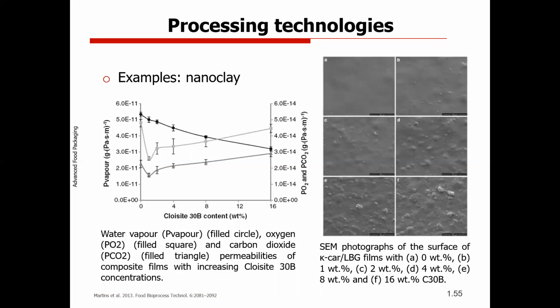Another of the examples that I bring today is the incorporation of nanoclay in polysaccharide-based films. Nanoclay is very well known in the packaging industry. It's used as a reinforcing agent, and it also has some properties as an antimicrobial agent. What we tried here was to study different levels of incorporation of these nanoclays in these films. You can see here on your right some scanning electron microscopy images. We don't have any incorporation, then we are increasing from 1, 2, 4, 8, and 16% of this Cloisite 30B, which is a nanoclay.